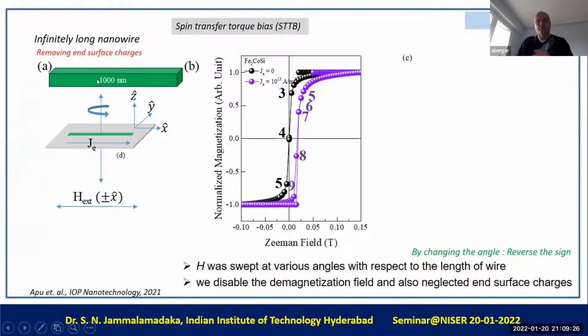Right, but what is the source? What do you envision the source of that spin polarized current to be? We wanted to create some kind of spin transfer torque in the system. No, I understand, but where is it coming from? It is from the simulation, actually. No, I know, but you were saying that you were hoping to find an experiment. But if you assume a fixed spin polarized current that is not dependent on the magnetic state of the sample. Yeah, it doesn't depend on the magnetic state of the sample, yes.